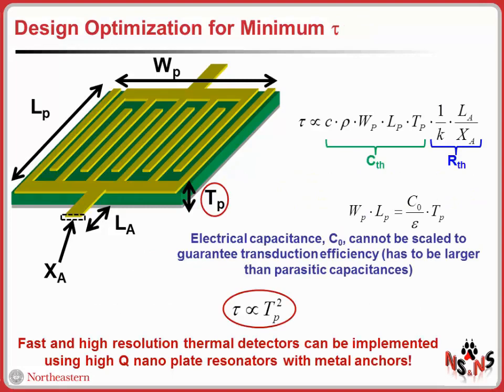But now, given this large thermal resistance, if you want to maintain a relatively low time constant, what is really crucial is to scale the volume of the device. Right? We need to reduce the thermal capacitance of the resonator. And in principle, lateral scaling of the device would be sufficient in order to reduce the volume and therefore reduce the thermal capacitance. But the problem is that simple lateral scaling would drastically reduce the electrical capacitance of these piezoelectric transducers substantially, and that would become comparable to parasitics that are on the substrate, and that would drastically reduce the transduction efficiency of the device. So basically, we would couple a lot of energy to parasitics rather than the piezoelectric resonator itself.